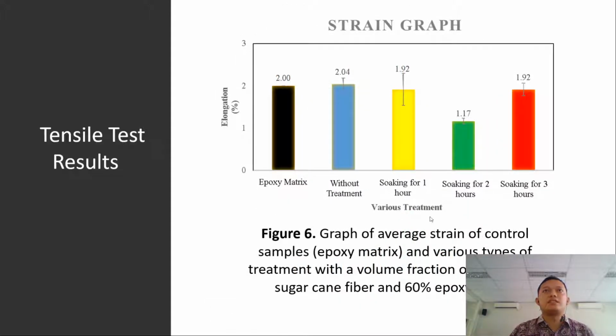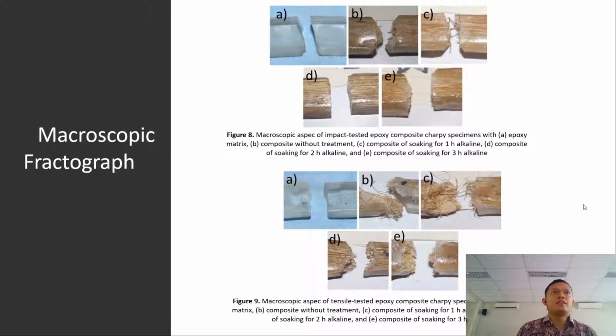And this is the strain graph. The decrease in strain value on composites with 5% NaOH for 2 hours is supported by the theory that plant fibers in general have higher stiffness and strength, which gives an effect based on extraction method. In this case, the type of plant fiber was bagasse with the alkalization extraction method. And this is about the microscopic fractograph after impact and tensile. The failures that occurred were dominated by fiber pull out, which means the fiber absorbs more energy, so the interface between the bagasse fiber and the epoxy matrix was stronger.